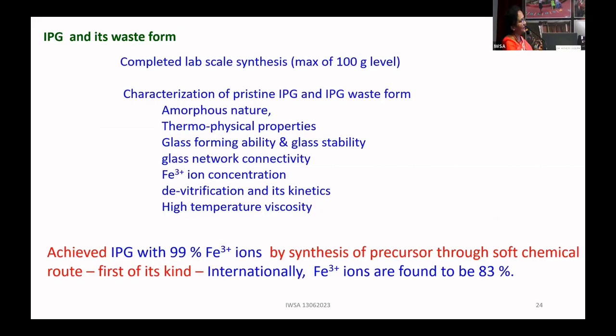And these types of works have been done on an R&D scale. All the characterization with respect to thermophysical properties, forming ability, and glass stability is itself a typical topic which can go for 1 hour. But what we would like to tell you is why this Indo-UK program started: we were able to give an iron phosphate glass with less than 1% of iron 2+ concentration, which internationally they could not do. They could only complete up to 17% of iron 2+, whereas we achieved, through a soft chemical route, 99% iron phosphate glass with iron 3+ ion.